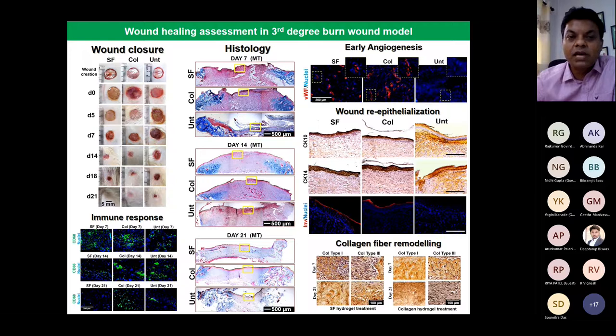If you look at the wound closure, in less than 10 days we have complete wound closure. And when we look at the immune response, we found it to be a compatible material. We have early angiogenesis, similar to collagen, meaning blood vessels for non-healing wounds. We all know angiogenesis is very critical, and this material allows a lot of fresh blood vessels to be formed, which allows the regeneration to happen faster.